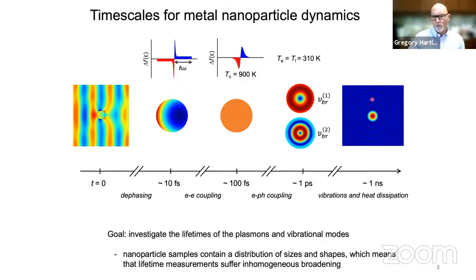So in this talk, I'm going to concentrate on the processes at the start, the dephasing of the plasmon, and at the end, how these vibrational modes lose energy to their environment, and not worry too much about the stuff in the middle, okay? Because we're focusing on lifetimes, we're going to measure the lifetimes of the plasmons and the lifetimes of the vibrations. It turns out when you do an experiment on a sample of metal nanostructures that you might make or buy, there's a whole bunch of different sizes in that sample. So the lifetimes suffer from inhomogeneous broadening. If you want accurate information about the lifetimes, you really ought to do single particle experiments. And that's going to be a big part of the talk.